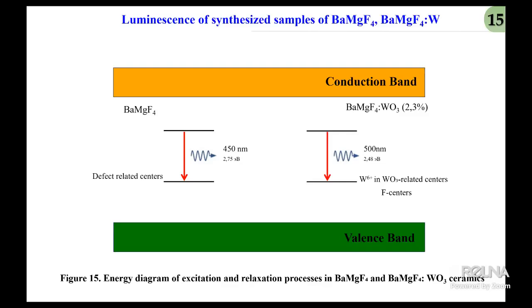This slide presents the energy diagram of excitation and relaxation processes in BaMgF4 and BaMgF4 with tungsten ceramics. In non-activated ceramics, luminescence in the 450 nanometer region is attributed to transitions involving defect centers in the matrix formed during radiation synthesis. These defects create localized states within the band gap through which radiative recombination of charge carriers occurs.